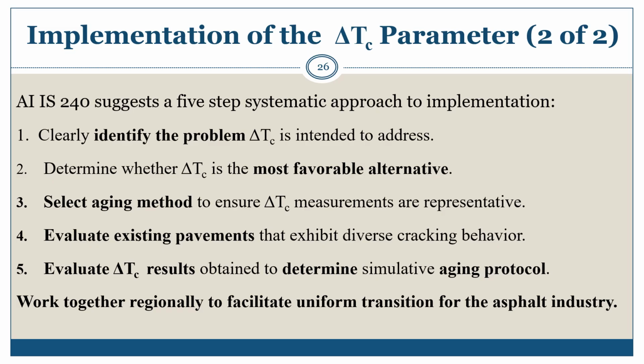Step 1, clearly identify the problem delta TC is intended to address. Step 2, determine whether delta TC is the most favorable alternative. Step 3, select an aging method to ensure delta TC measurements are representative. Step 4, evaluate existing pavements that exhibit diverse cracking behavior. And step 5, evaluate delta TC results obtained to determine simulative aging protocol. A complementary element to the recommended framework is a concerted effort with all entities working together regionally to facilitate uniform transition for the asphalt industry.